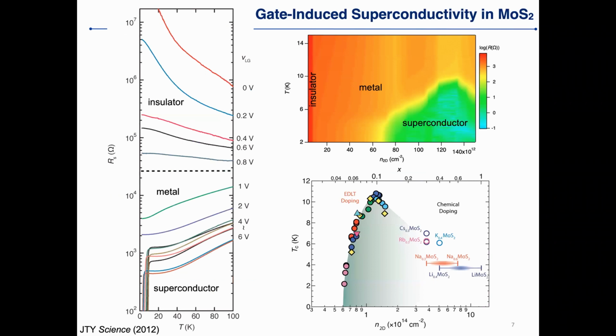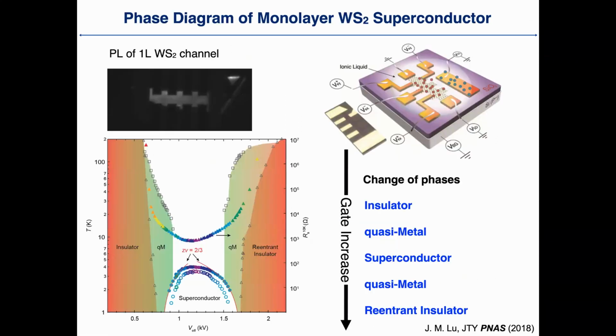And then another feature of this ionic gating is that we can study the phase diagram of the superconductor as a function of carrier density, and we can access the phase region that is different from the previously studied phase by alkali metal doping through chemical intercalation. And here we can use one sample and apply a gate voltage so that we can access the different superconducting states. One feature we can see here is that we have a dome-like shape as a function of the carrier density, and this puzzled us for a while. So then we go to a different sample.